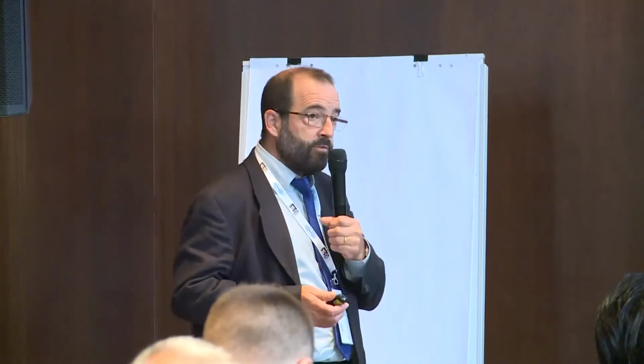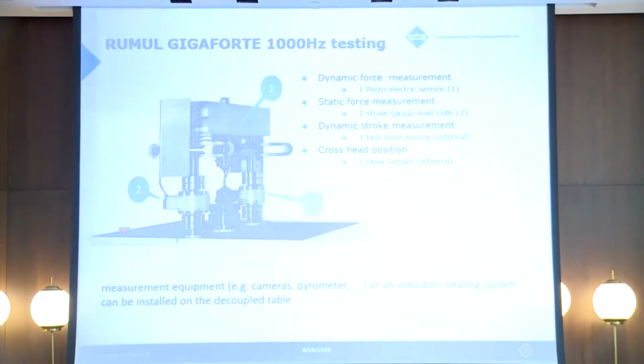A challenge is the correct measurement of the load in such a system, at 1000 hertz, because of the high acceleration. So we have a 2 force measurement system in place, one for the dynamic force, which is in the upper part, which sees less vibration, directly above the fixture between the crosshead and the fixture. And we have 2 normal Rummel strain gauge load cells at both columns to measure the static force. The piezoelectric system has the advantage of a small mass and a high stiffness, so we do not lower the frequency with the measurement system.